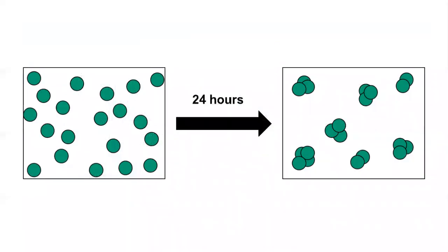This happens because each sample contains a fixed number of nanoparticles. As these particles agglomerate, they'll form a smaller number of larger sized particles. So with the image here, each frame is supposed to represent 20 particles. At the left hand, this is what the sample looks like just after I've mixed it. And then on the right hand side, this is effectively supposed to demonstrate what we start to see after 24 hours of incubation time.